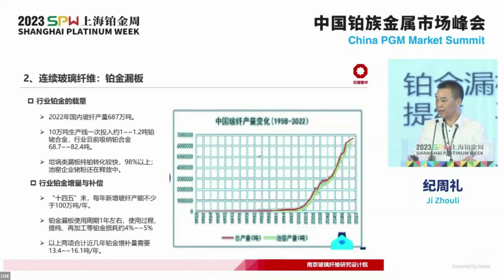So now let's look at the consumption volume of platinum in our industry. In 2022, the fiberglass production amounted to 6.8 million metric tons. If we are to have a 100,000 ton production line, then it would need 1 to 1.2 metric tons of platinum and rhodium alloy. So far, we have absorbed in our industry 68.7 to 82.4 metric tons of the alloy.